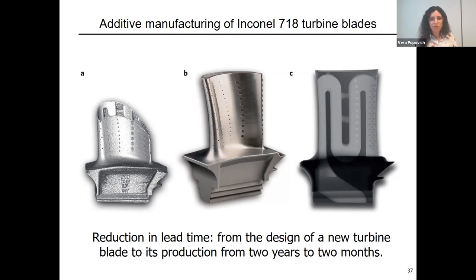It can form 3D shapes that are very complicated, almost unlimited in design. And it can reduce the lead time, and that's one of the actual reasons why these 3D technologies are used: first the lead time, and second, accessibility anywhere remote to replace parts. So with this technology, you can reduce the lead time from the design of new turbine blades to their production from, let's say, 2 years to 2 months. That just gives you an order of magnitude of what's possible.